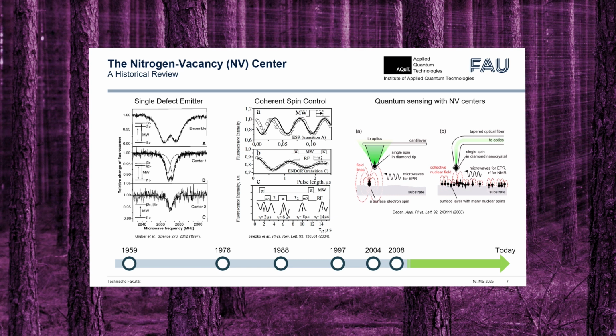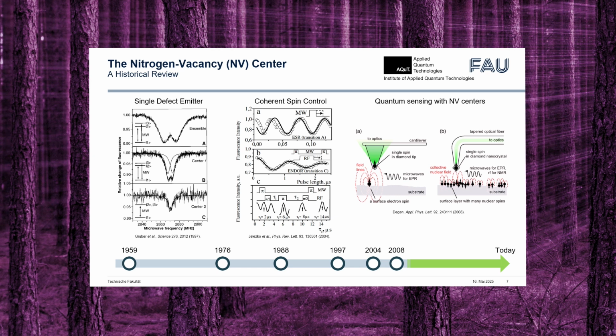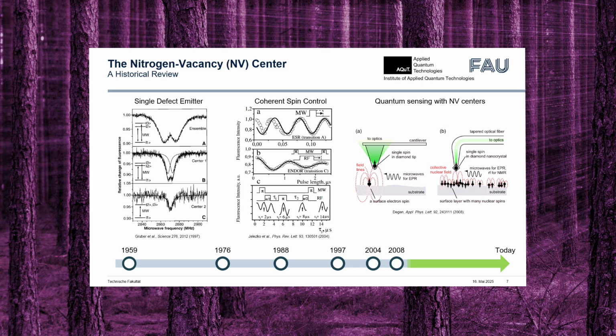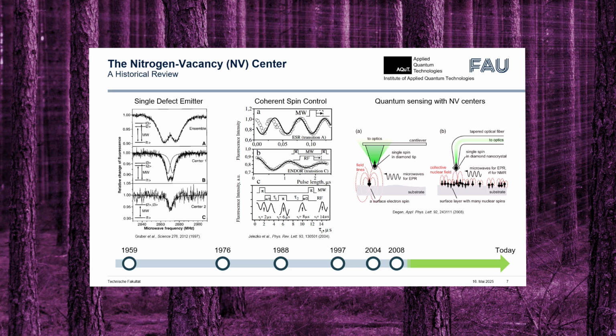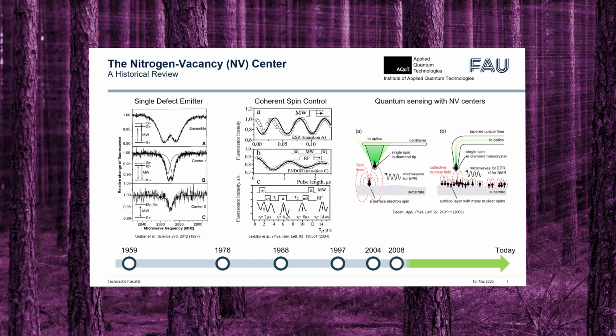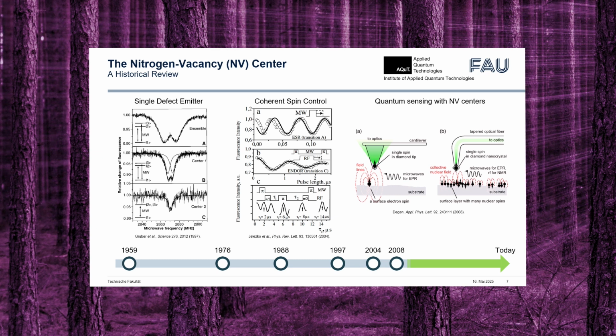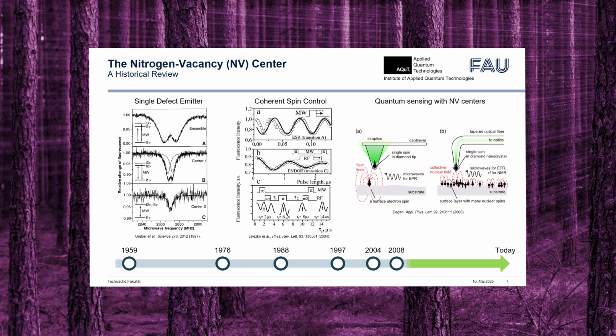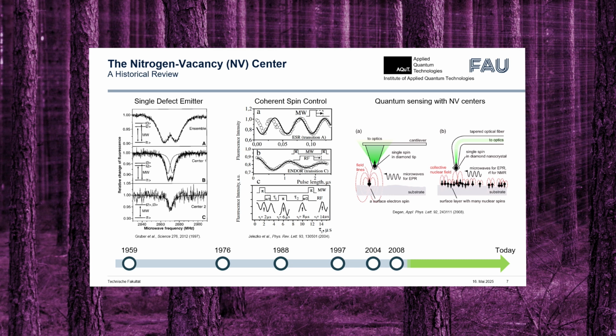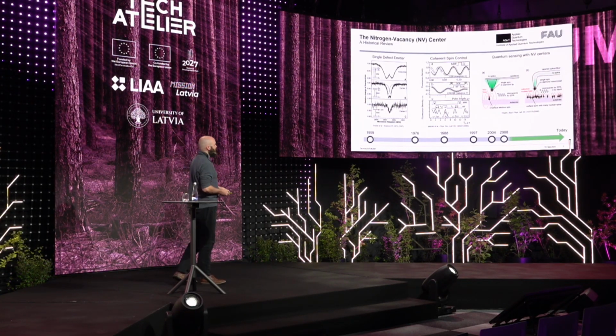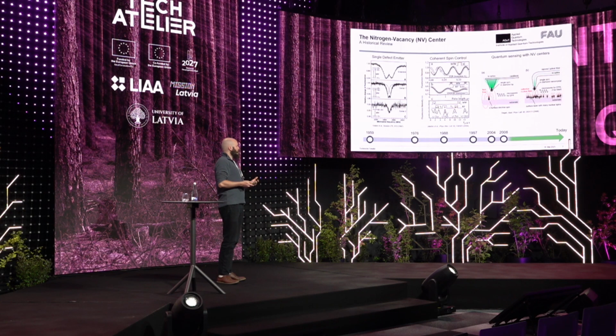And we use these incredible sensitivities of our vacancy to the environment in order to perform measurements that haven't been possible before. We could imagine, or it has been proposed and it has been experimentally shown more than 15 years ago, that you could insert a nitrogen vacancy into the tip of an atomic force microscope in order to scan across a substrate and detect the signal of a single electron on the surface of the substrate using the NV center as a sensor.